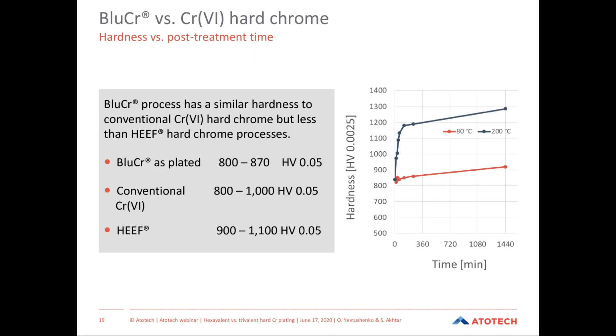So here on this slide, you can see very well how the hardness evolves with time and temperature. At a temperature like 80 degrees C, over time not much hardness increase is to be expected. But if you go for higher temperatures, in this case 200 degrees C, then you can see that both temperature and also time are important. To summarize the hardness, we can say that in the blue chromium process, the parts have similar hardness to conventional hexavalent chromium, but at the same time they are a bit softer than HEEF hard chromium processes, as plated.